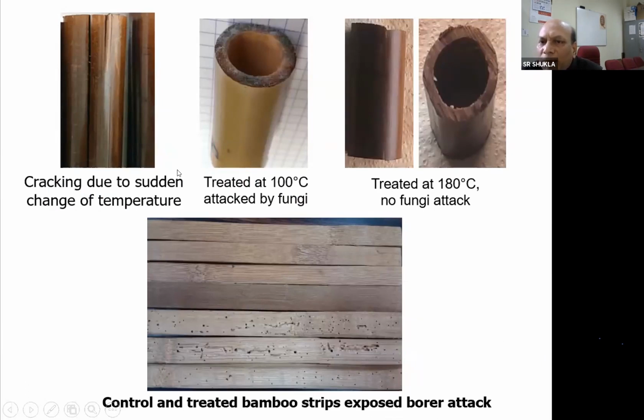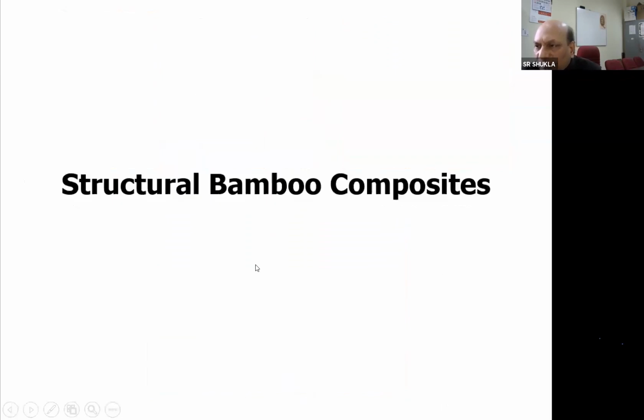This slide shows the treated bamboo at 180 degrees centigrade. There is no fungal attack, whereas in the bamboo treated at 100 degrees centigrade, a small fungal attack can be seen. And this shows the control and treated bamboo strips exposed to borer. You can see these bamboo strips, I have been keeping them together for more than 3 to 4 years now. These are the control bamboo strips which are being attacked by the borers a lot, but these are the treated bamboo strips. They are not touched by the borers. So this clearly shows that thermally treated bamboo is much more durable compared to control bamboo, without the use of any chemical.